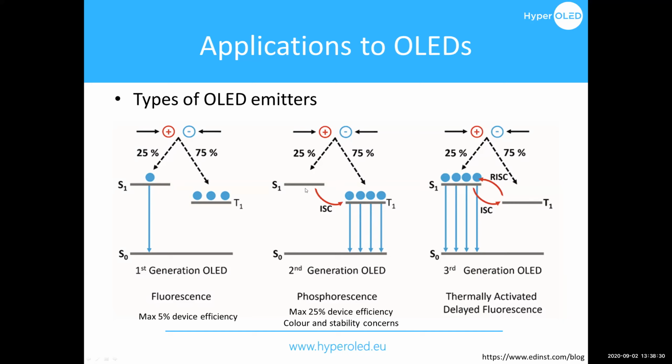And those really, really high accessible electronic states in molecular devices means that you start running into the barrier of sort of bond dissociation energy for the complexes that you're looking at. So it turns out that it's extremely hard to make good phosphorescent materials that are blue and have long lifetimes, because as you're injecting charges into them, you're populating singlet states. Those singlet states have a chance of breaking a bond somewhere, and so the LED dies pretty quickly as a result, just because of the energetics of the phosphorescent emitters themselves.